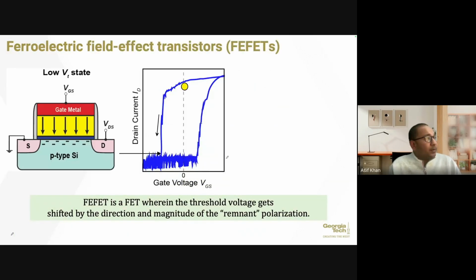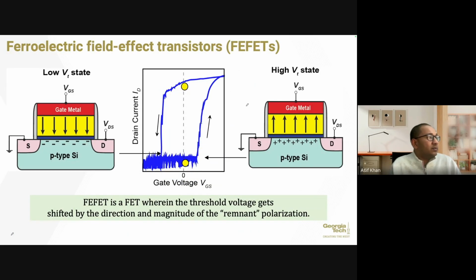And one level up, whenever we have a dielectric material or an insulating material, we always tend to put it in contact with a semiconductor. We can combine it with a semiconductor to make it into a transistor structure. And if we take a transistor and use a ferroelectric material as the gate oxide, then the direction of the polarization can modulate the current that will flow between the source and drain. And then the current between the source and drain will actually depend on the direction of the polarization.